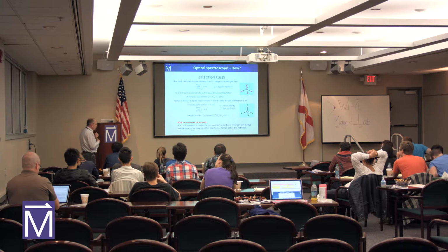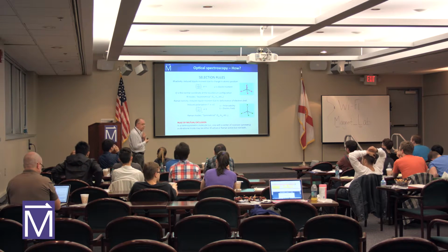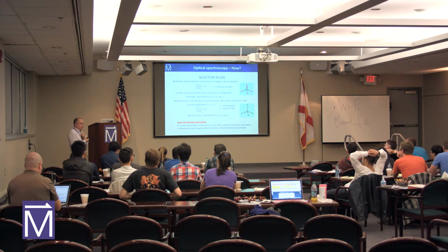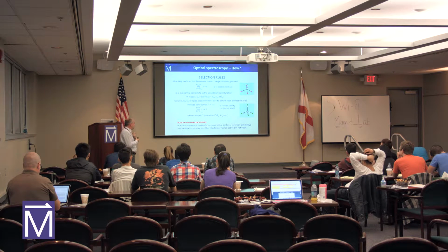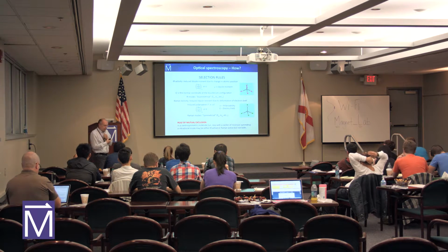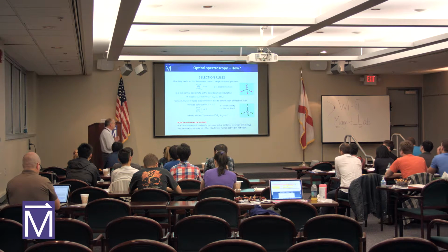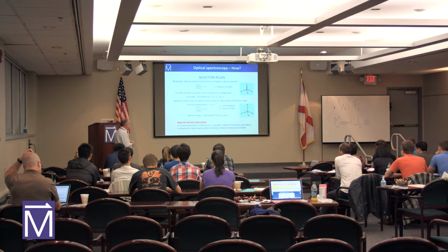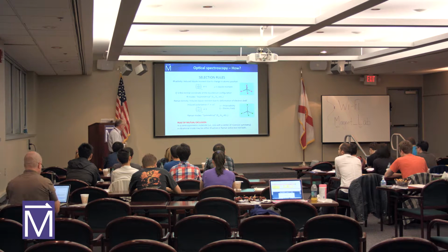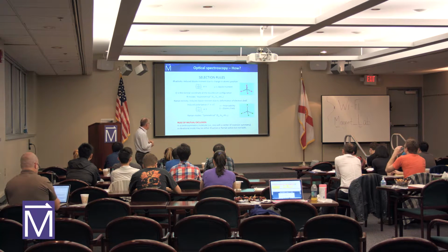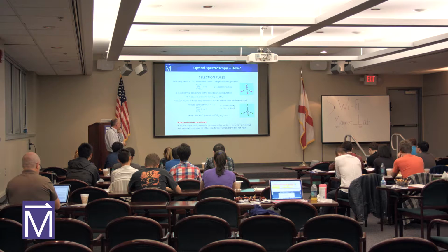Why is it so good for physics and chemistry, particularly Raman spectroscopy and infrared spectroscopy? It's a very sensitive structural probe. It follows selection rules very strictly, because IR activity is related to the dipole transition, just the displacement of atoms which produce a net dipole moment. And that's how it can be detected with light. Raman activity is something totally different. It's about the polarizability of an atom. And it has a very simple rule of mutual exclusion. So in a centrosymmetric system, a vibrational mode may be either IR active or Raman active, but not both. And by doing polarization-resolved measurements, you can deduce in what direction this movement of atoms happens.